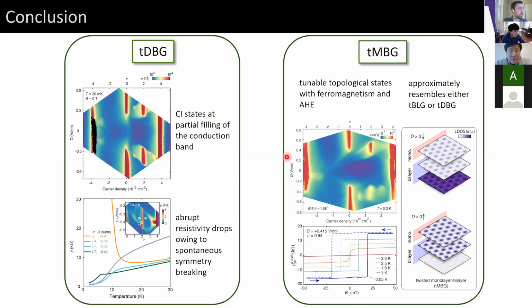So in the double layer twisted system, did you use a magnetic field to see whether there's a magnetoresistance effect to indicate whether it's superconducting, or other effects such as weak localization or emergence of magnetism? Yeah. We look for all of those things. The long story short is that there's not a strong magnetoresistance as we apply a magnetic field in these states. So I think I can show you.